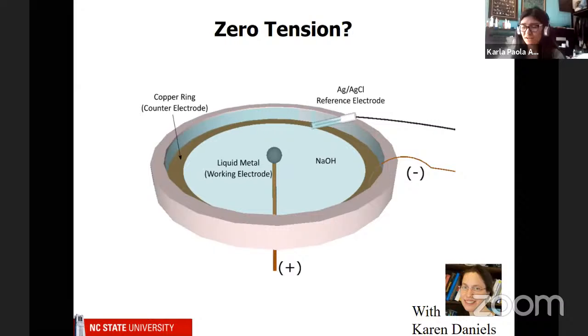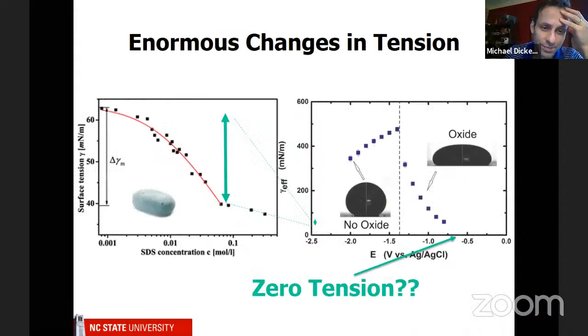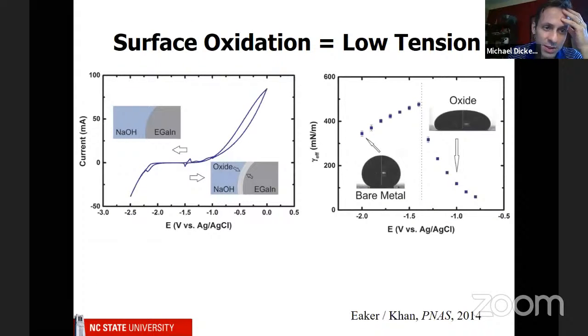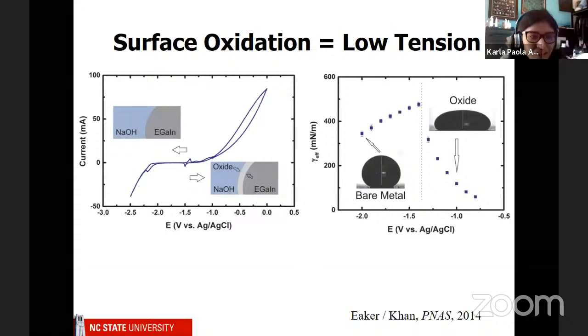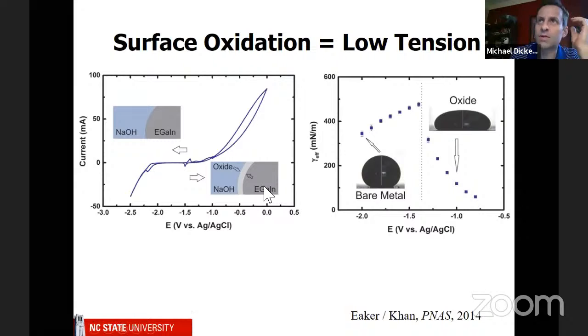But you can measure the current? Yep, we've measured it, and we're still studying this. It's actually more complicated than I explained. So this is actually where we measure the current. If you look, it's a little hard to see, but this is 0 current. So we start right around here, and we start applying a positive voltage. We move to the right, and you see there's a little bump. That's actually where the oxide first deposits.